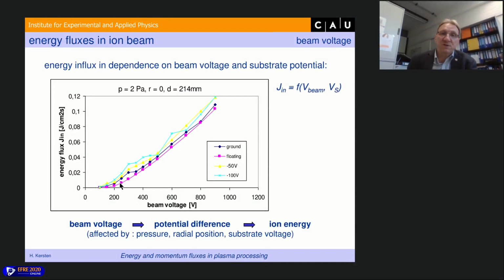And of course, what you expect, if we increase the beam voltage, we increase the kinetic energy of the extracted ions, and so the energy influx is increasing. This is clear, but also if we give an additional bias voltage to our probe, then if it is a floating probe, this is the magenta color, it's the lowest value compared to this blue value, which is minus 100 volts. So there is an additional kinetic energy due to the bias of our probe.